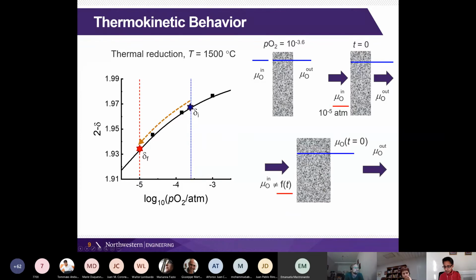Now, if we look at what happens with time, the incoming gas has the same chemical potential throughout, and the outgoing gas is slowly moving down in its chemical potential. And again, our assumptions are that the chemical potential is constant across this porous material, that it's in equilibrium with the gas, so this has nice access to the gas.